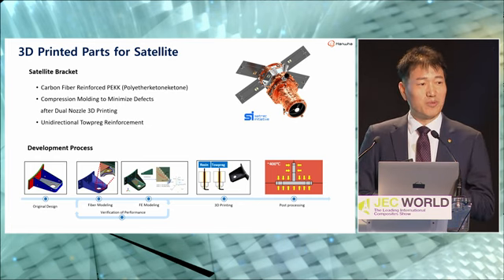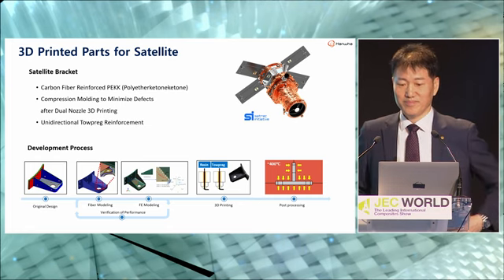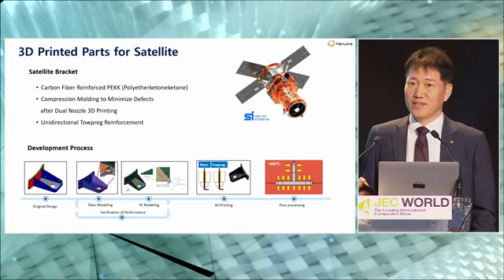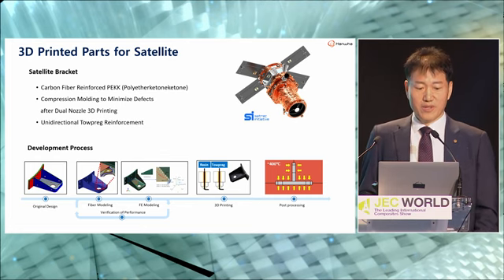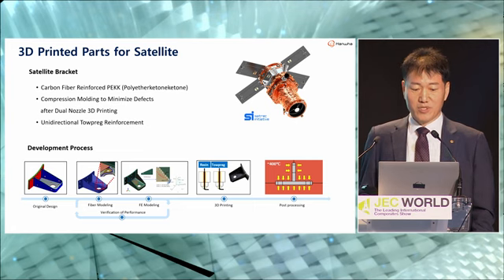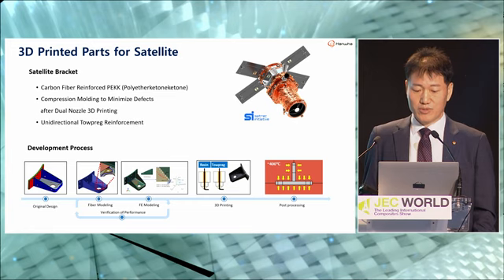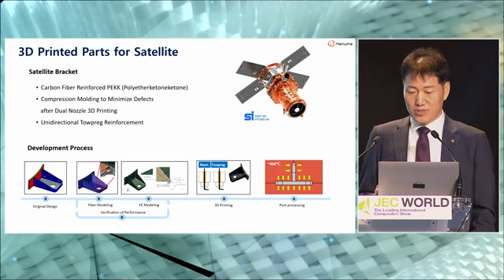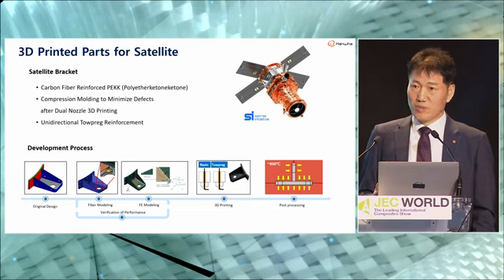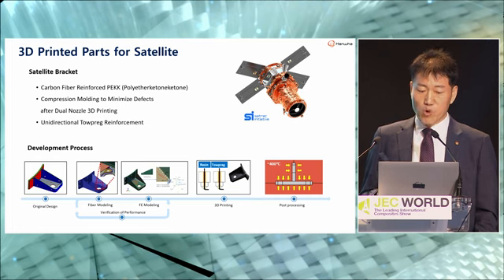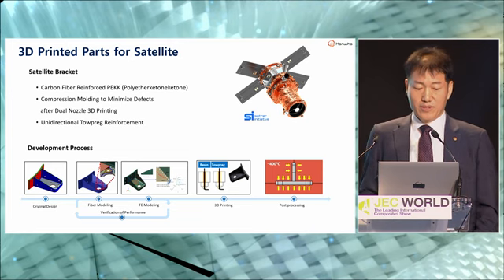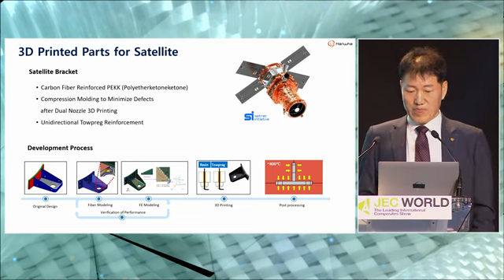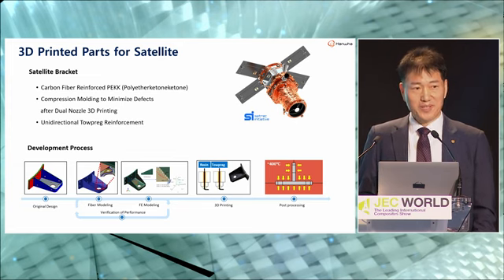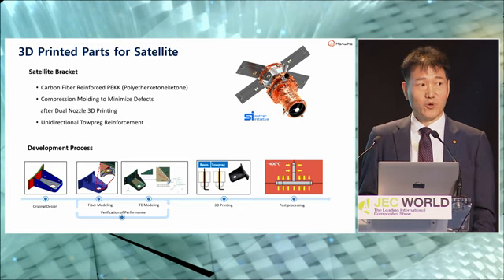The next one is 3D printed parts for satellites. We are co-working with SatRec-i, a high-resolution imaging satellite maker headquartered in Korea. We want to use carbon fiber reinforced PEKK, polyetherketoneketone. We tried to use dual nozzle 3D printing, followed by compression molding to minimize voids. It's a small but very high performance part, so we tried to use 3D printing technology instead of autoclave.